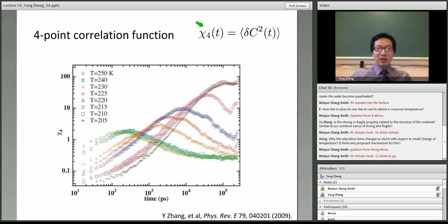So the key experimental challenge is that chi4 is a 4-point correlation function. In experiments, by doing a scattering experiment or perturbation experiment, because of the linear response theory, we can only have a 2-point correlation function. So in principle, determining chi4 would be difficult. Actually, I'm trying to develop methods combining computer simulations and neutron scattering to try to determine such a function experimentally.